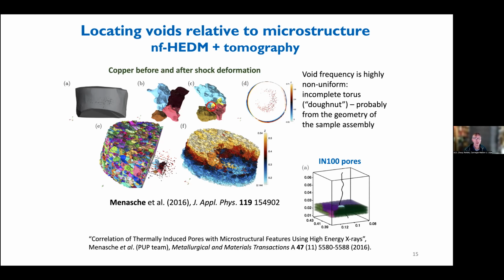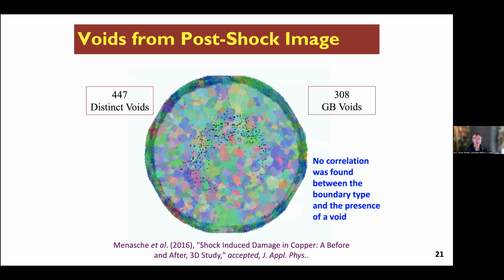So let me elaborate and skip over the IN100 pores. David Menasche in particular was able to take that void structure, lay it on top of, register it with the original measured microstructure. There were north of 400 voids, of which about 3/4 of them were close enough to grain boundaries to be considered grain boundary voids. So it was in fact grain boundaries that we mainly focused on. Since a grain boundary is a dividing point between two different orientations of the crystalline material, and presumed to be a place that would maximize any, shall we say, untoward behavior.